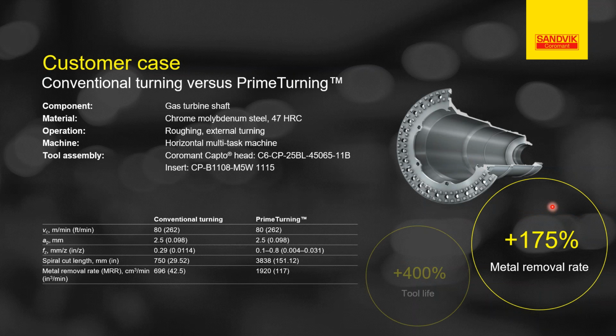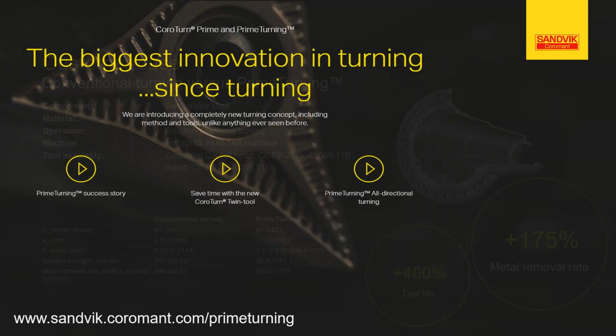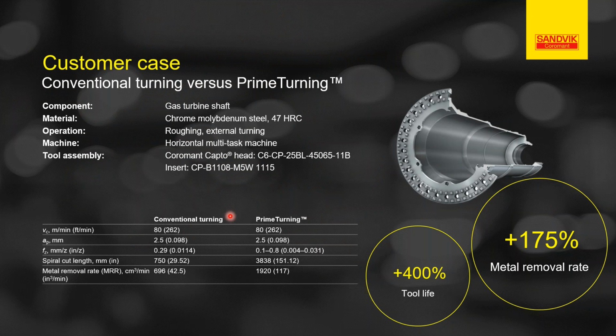This is an example on a gas turbine shaft. You can see here that we can move from a conventional turning where we have 0.3 millimeters in feed to 0.8, so more than 2 times, with a metal removal rate of 175% and an increase of tool life too.